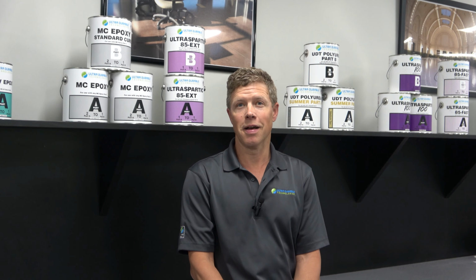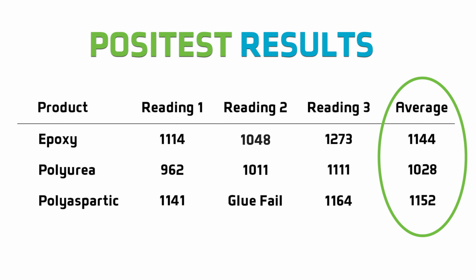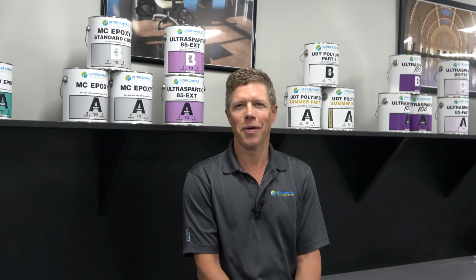Let's review the results. Here are the average PosiTest readings. You can see that all 3 have very similar results. In fact, all of them resulted in concrete failure, except for one where the glue failed to bond to the Polyaspartic. Good coating adhesion is typically considered to be at or above 400 psi, especially when the failure mode is due to substrate failure. That indicates that the coating has bonded well and can withstand significant stress.